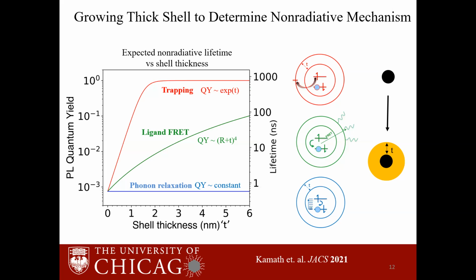The ligand FRET just depends on the absorption of the ligands, so we do not expect to see any temperature dependence; it should be flat. Trapping is usually an activated dependence, so we should see an Arrhenius type exponential behavior. And for phonon relaxation, when the phonon frequency is quite low, you will expect the temperature dependence to be temperature raised to the number of phonon modes, so T raised to 15 or T raised to 10. I don't have a graph, but that T raised to 15 trend is a much stronger dependence than the trapping. So that's another way where we can distinguish the mechanisms.